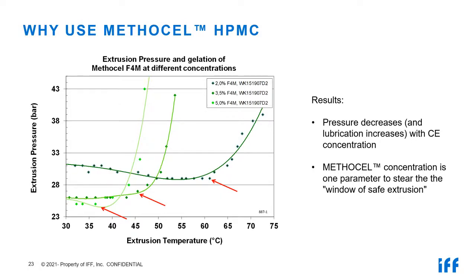Second case with 3.5% of F4M. Now we are coming to the second line, starting at 26 bars extrusion pressure. You can see that the extrusion pressure drops significantly, so the lubrication is definitely better. This looks very good. This is an advantage, but at the same time you get a disadvantage because the